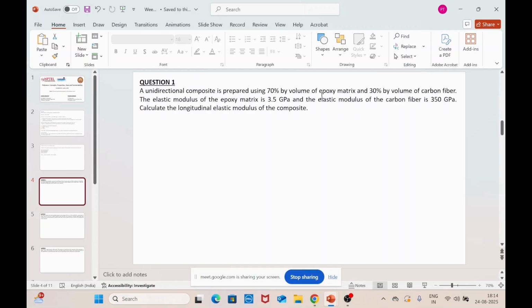So a unidirectional composite is prepared by using 70 percentage by volume of epoxy matrix and 30 percentage of carbon fiber. The elastic modulus is 3.5 gigapascal for the epoxy matrix, and for the carbon fiber it is 350 gigapascal. Calculate the longitudinal elastic modulus of the composite.